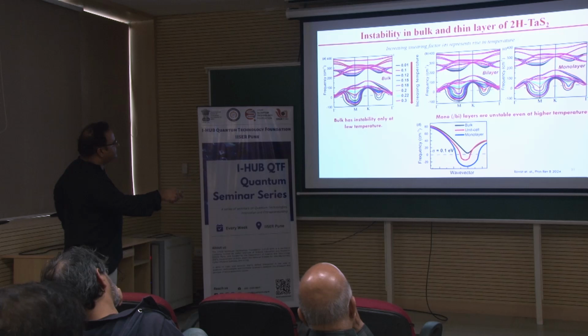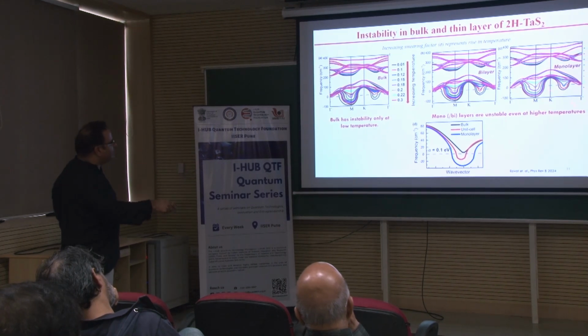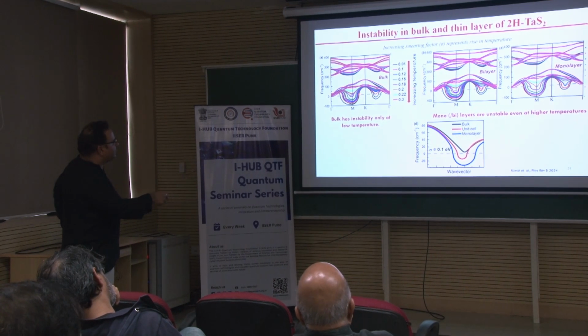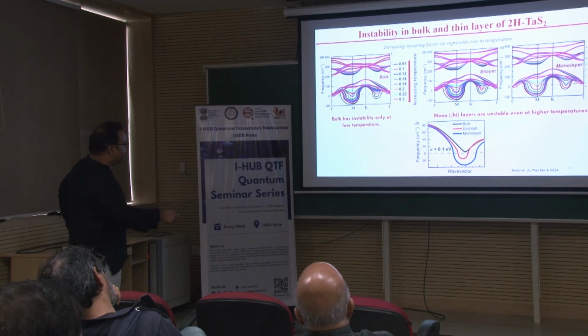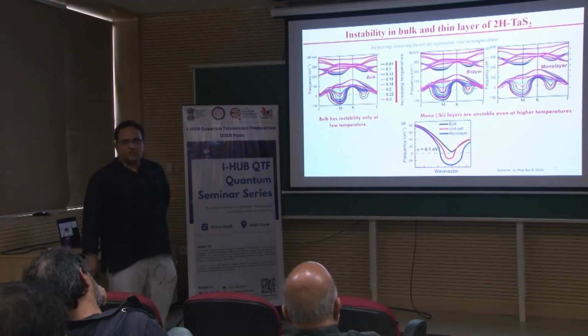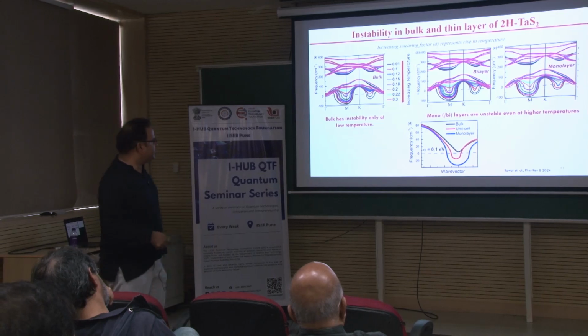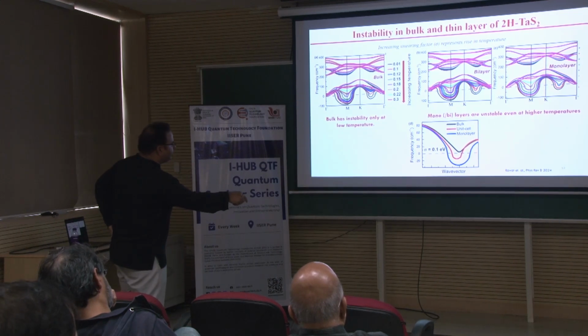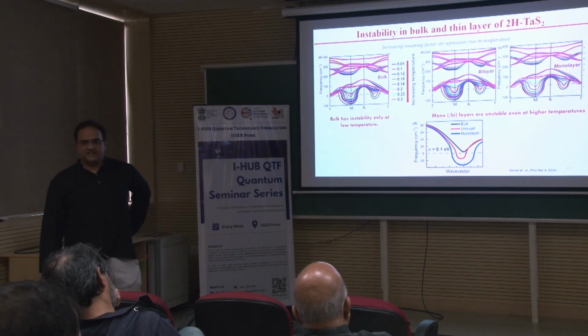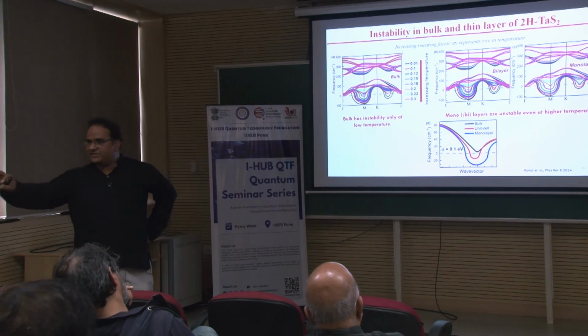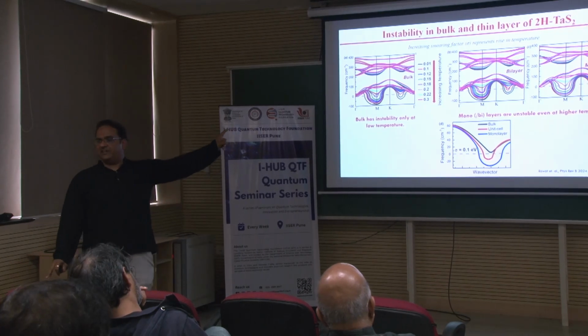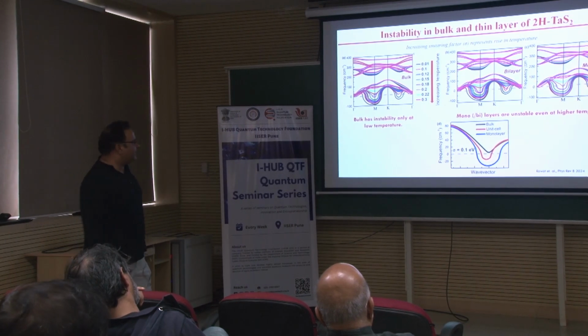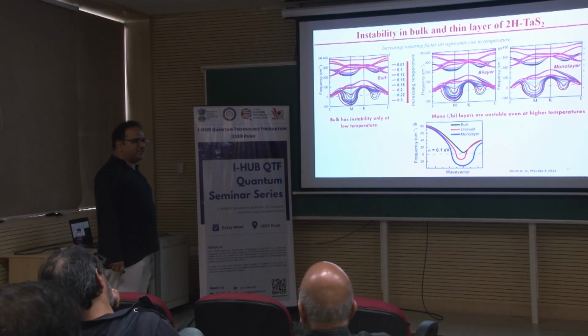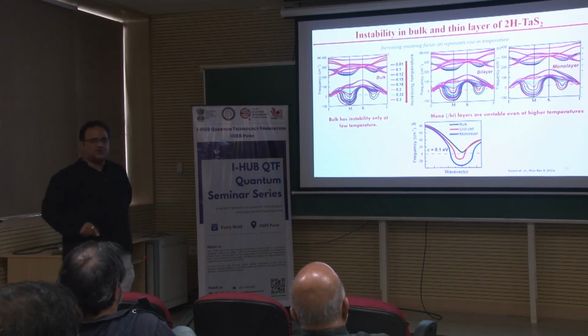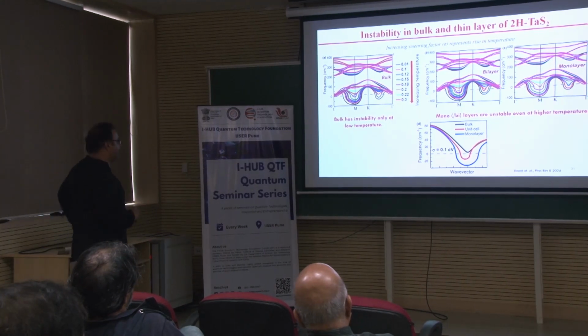So, this is bulk, this is bilayer, this is monolayer, but you will not be able to conclude from this, but you will be able to conclude here. This shows almost like 200 Kelvin temperature. This is my monolayer, this is my bilayer, and this is bulk. So, bulk does not have any negative frequency, no instabilities at higher temperature like 200 Kelvin, but bilayer or monolayer can have these charge density wave instabilities even up to 200 Kelvin.